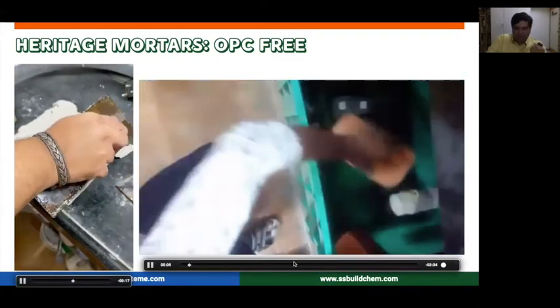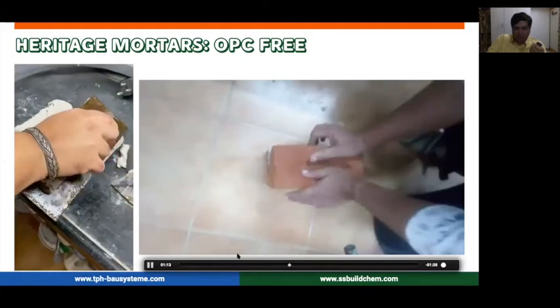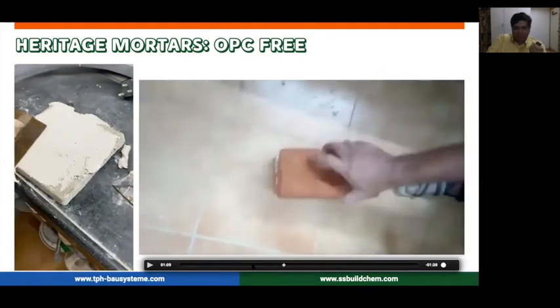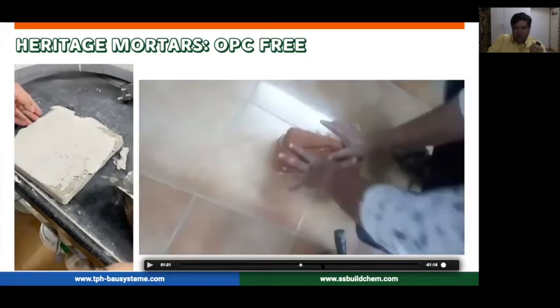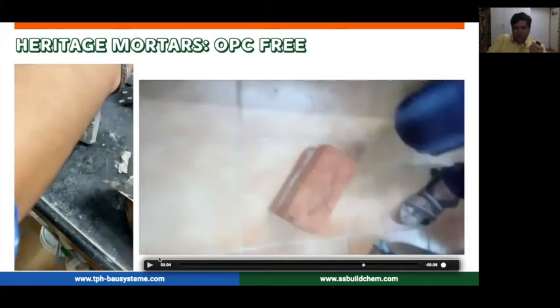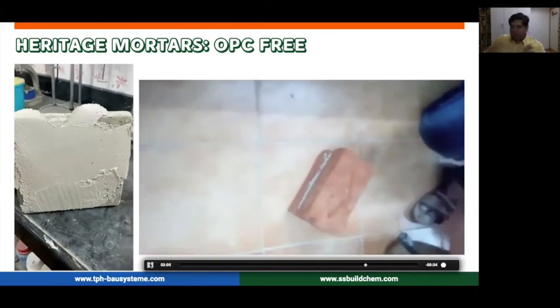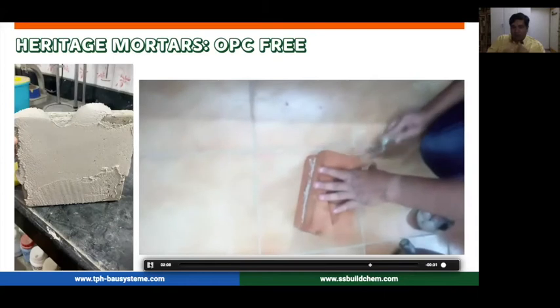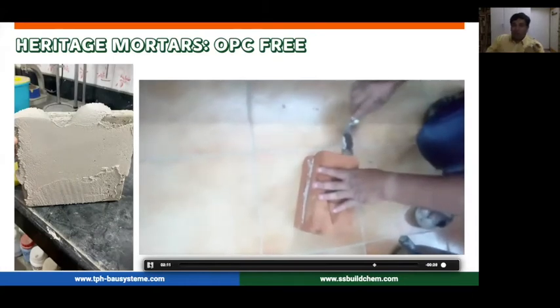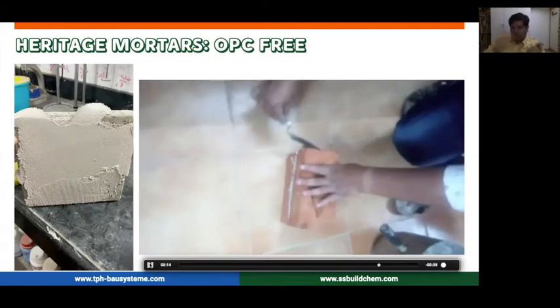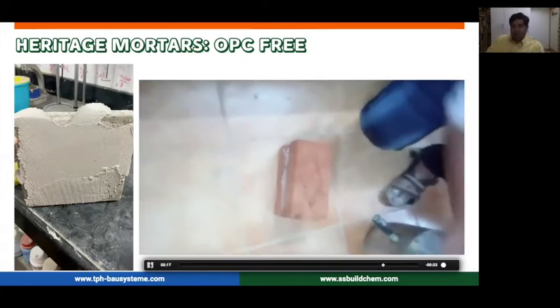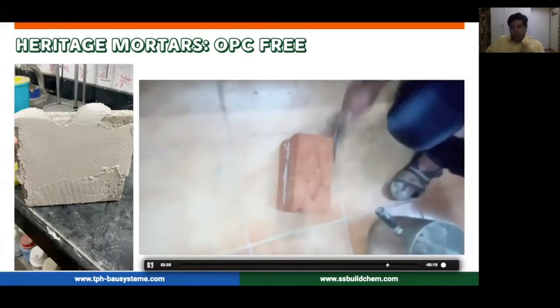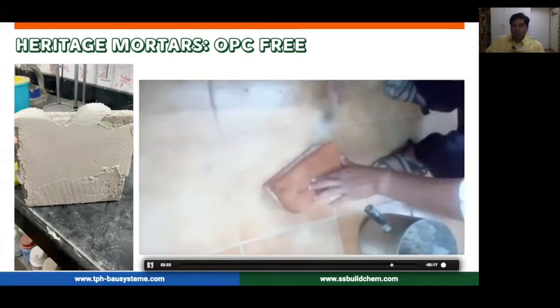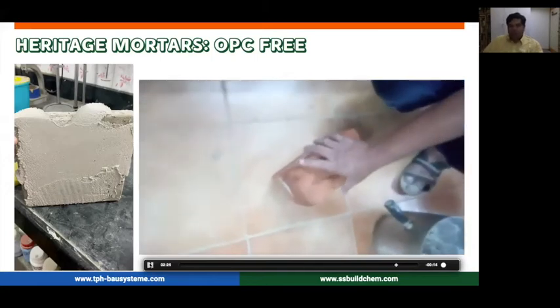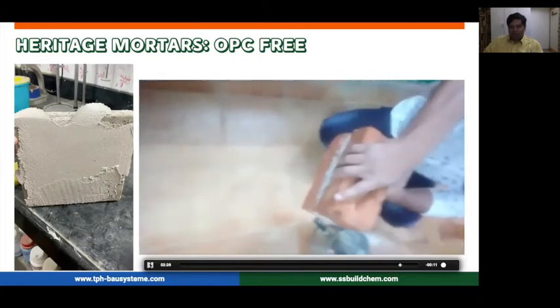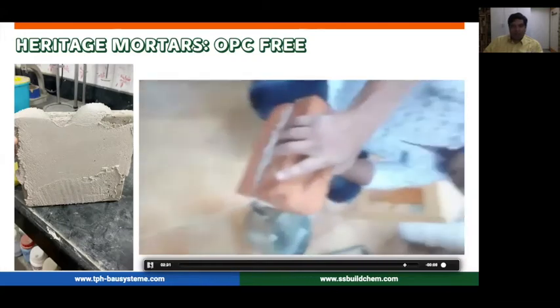This is also one more demo which shows you the kind of bond strength that you can see. So basically, this mortar was applied onto two bricks, and simply those bricks are put together, and then you can see that it's a very tacky kind of material. It will stick well, so you can use it for old pointing, old plaster, restoration, and if there are certain broken pieces, then you can very easily use this mortar to fill in those broken pieces. So it's an additional kind of mortar that you can use, but only for old structures. Okay, you can see it's got very good bonding strength, so it will bond to pretty much